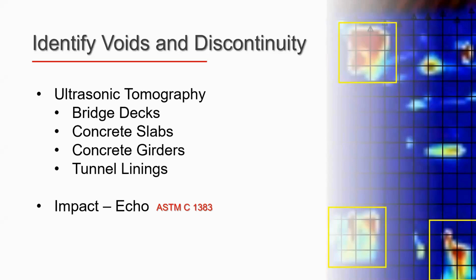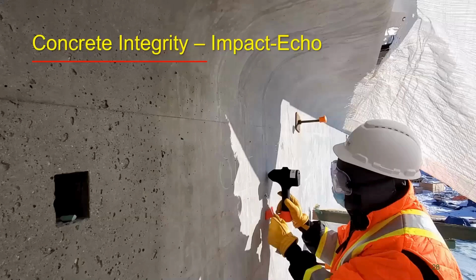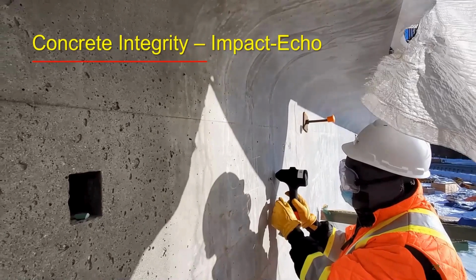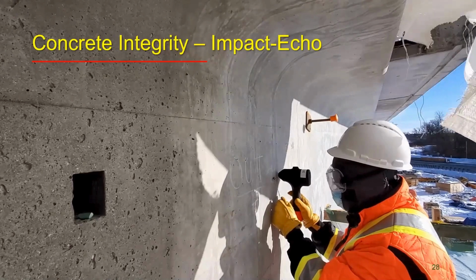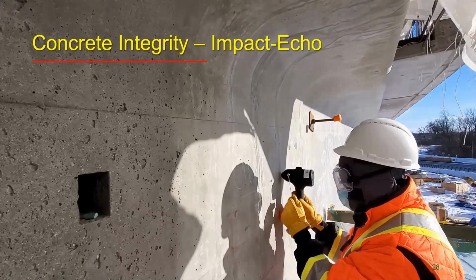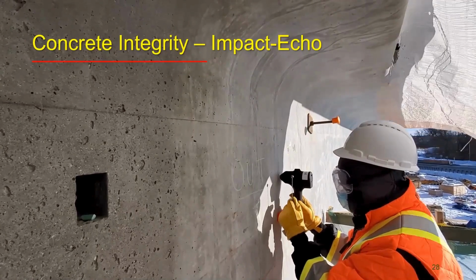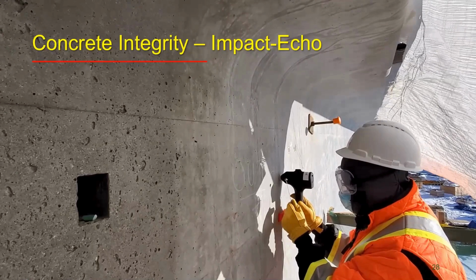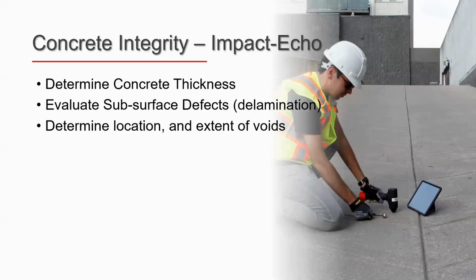Again, the technique can be used in ultrasonic tomography, and for bridge deck assessment, concrete slabs, parking garages, and tunnel linings. Another test in this group is impact echo testing. And impact echo testing is, again, when you have only one-sided access to an element, you can use impact echo to verify the integrity and quality of concrete material. It uses a stress wave method to verify the thickness of concrete components, and also to find any delamination or discontinuity in a parking garage slab or in a bridge deck slab. The test method will be able to help engineers identify those anomalies in the structure.